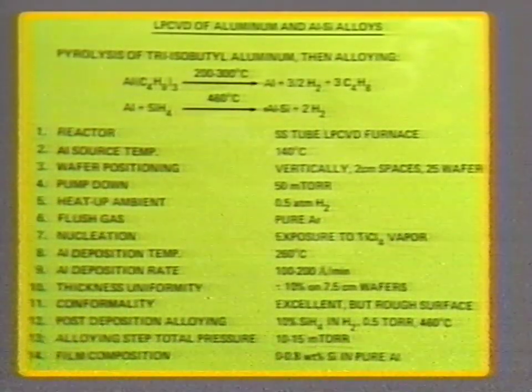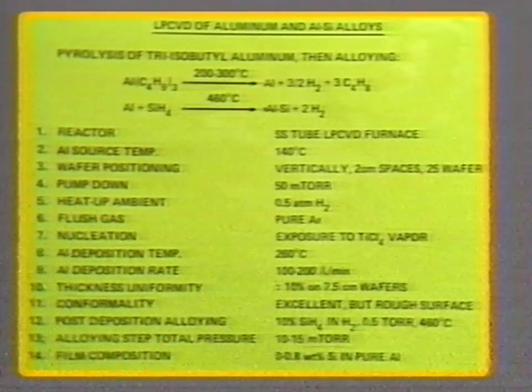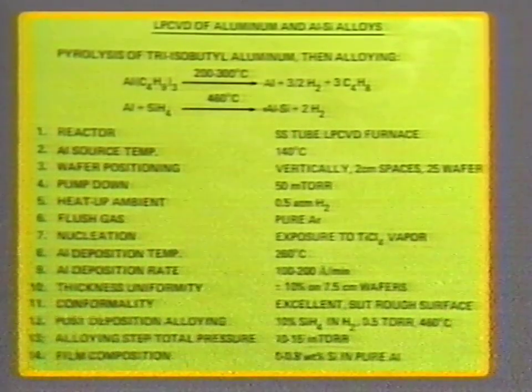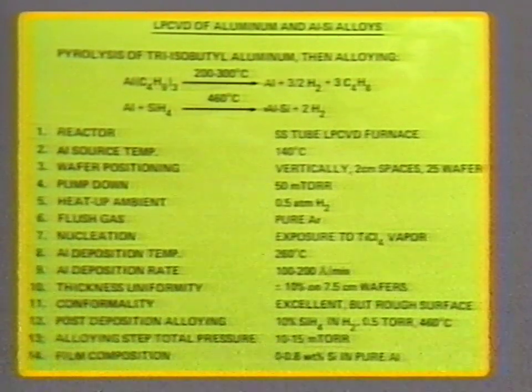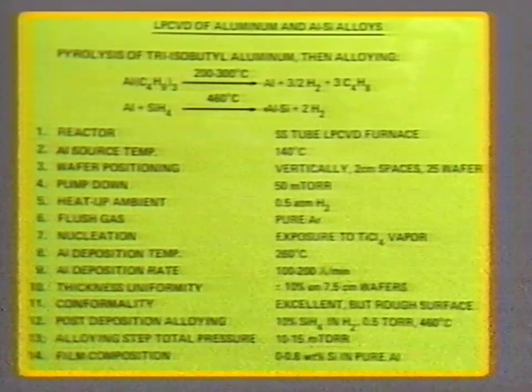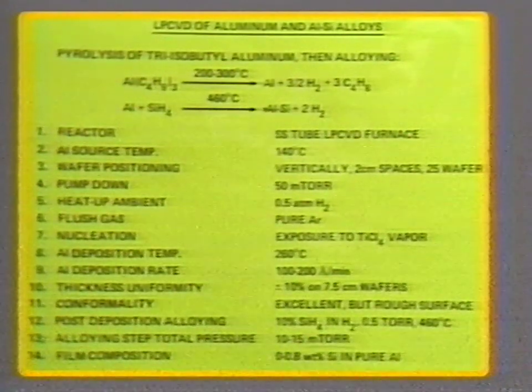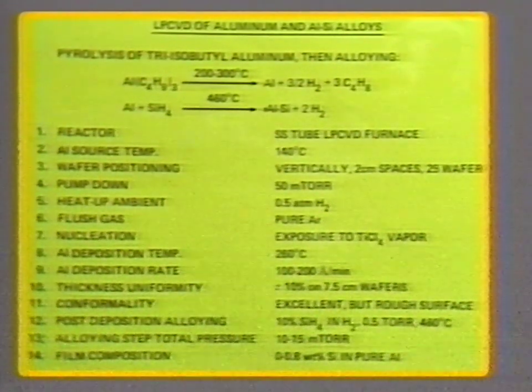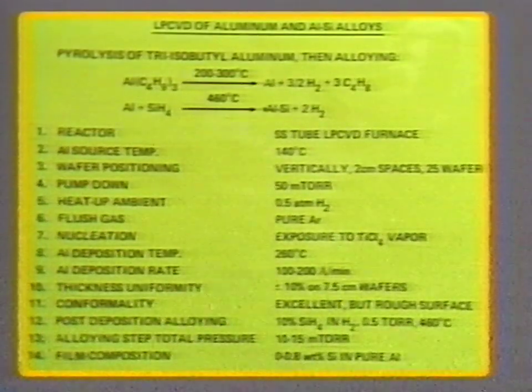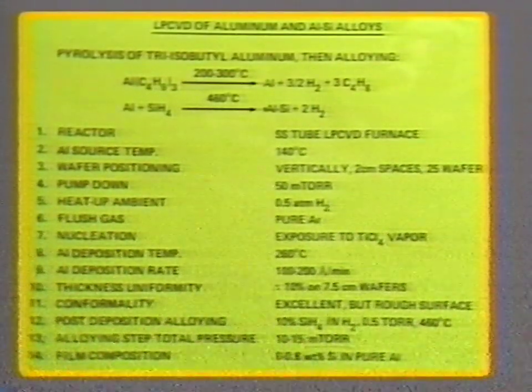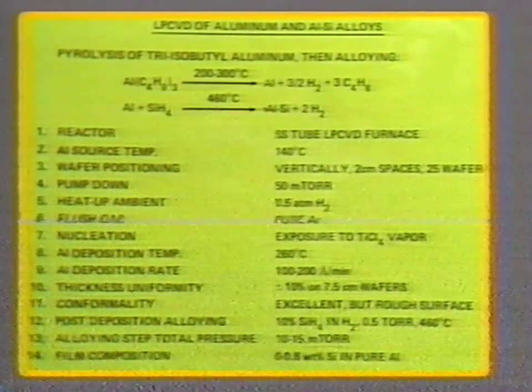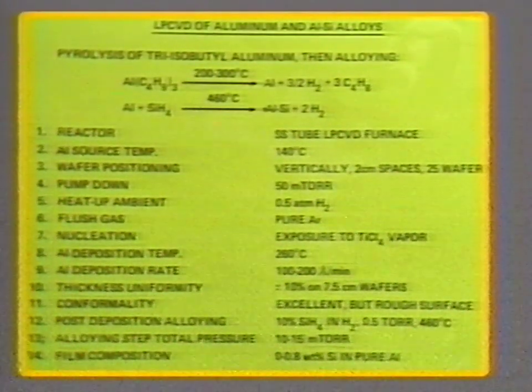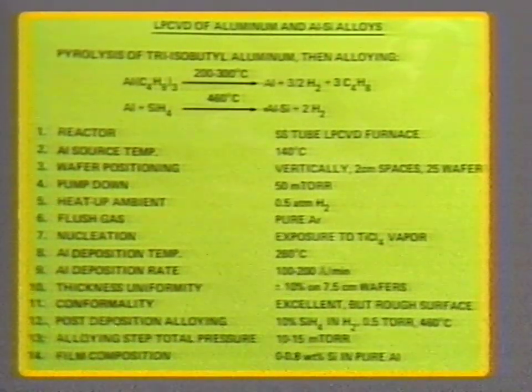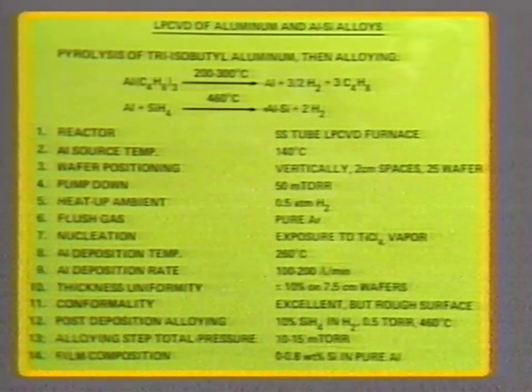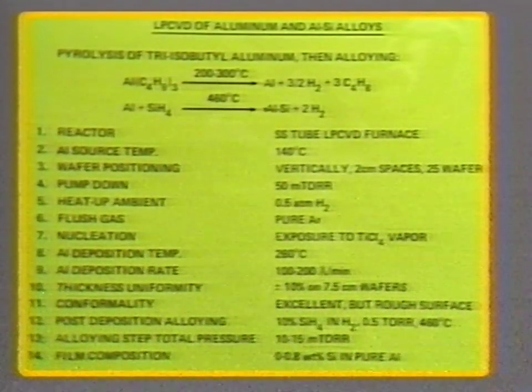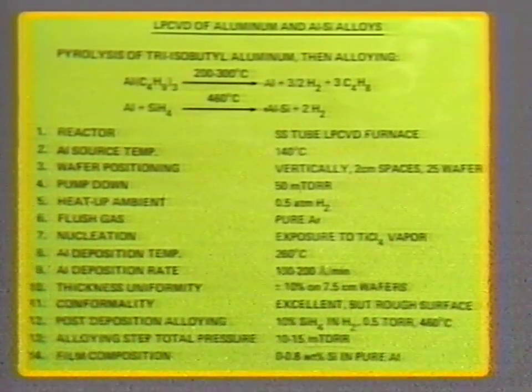We start off with an organometallic. Mainly in the past, so far, we have used tri-isobutyl aluminum, which dissociates in a temperature range of 200 to 300 degrees centigrade to elemental aluminum and side products which are swept out of the reaction chamber. As a secondary step, once we have the aluminum, we can now dope this with silane at a temperature of about 460 degrees C to produce a silicon aluminum alloy, which is the usual preferred type of aluminum used in silicon IC applications. Details are listed here that have been published so far.